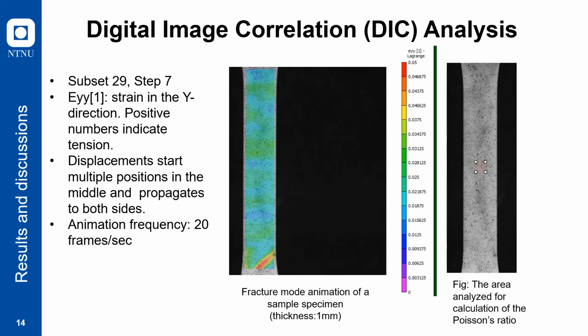So we also used digital image correlation, DIC for short, for analysis. For subset, we used 29. The subset means the area of the dots which was being tracked by the software for DIC. The larger the number, the larger the area it has, but also the larger the uncertainty. And for step, we select 7, which means for every 7 points, the software will take the average and use the average data to do the measurement and the calculations.